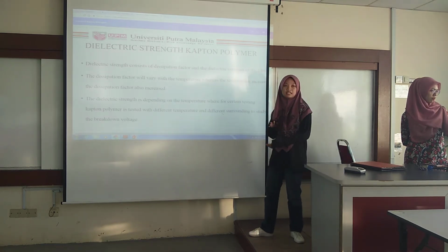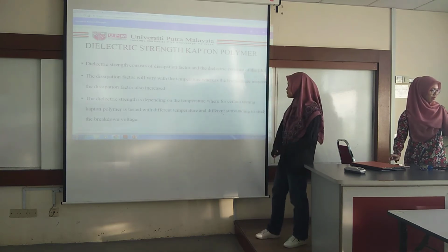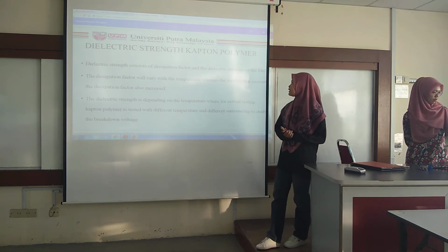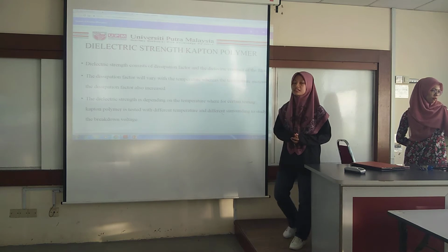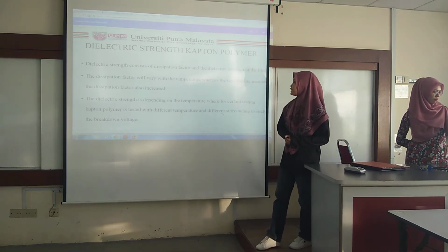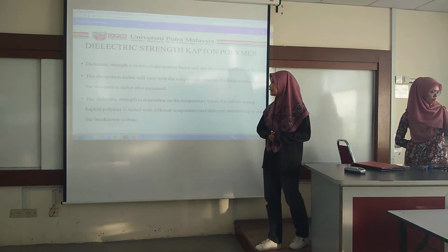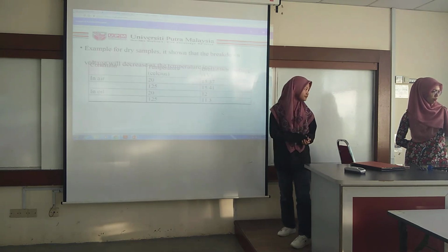Now for dielectric strength for Kapton polymer. Dielectric strength is related to the dissipation factor and dielectric constant of the film. The dissipation factor varies with temperature, where as the temperature increases, the dissipation factor also increases. The dielectric strength depends on the temperature, where for certain testing, Kapton polymer is tested with different temperatures and different surroundings to study the breakdown voltage.